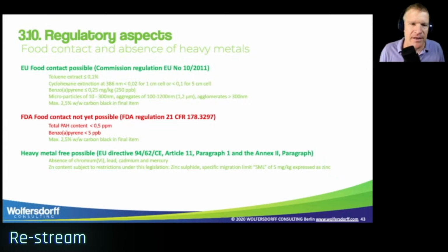In America, the regulation is much more stringent, and the FDA food contact is not yet possible. In my opinion, I haven't seen any recovered carbon black player that is fulfilling the very strict requirements of FDA food contact. The total PAH content needs to be below 0.5 ppm. I think the best I've seen is 1 ppm. The benzo[a]pyrene content needs to be lower than 5 parts per billion. This is super, super low and very, very difficult to achieve. Again, we have a limitation for the maximum carbon black or recovered carbon black content in the final item.